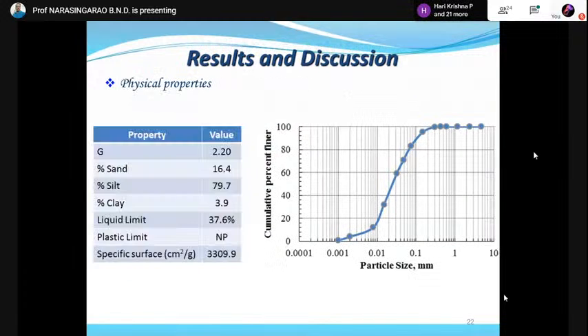So this is the grain size distribution of the fly ash. You can observe that 79.7% of the total fly ash sample is silt. So the problem is, fly ash has some liquid limit you can find out, but fly ash is basically non-plastic.